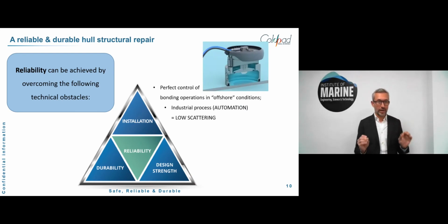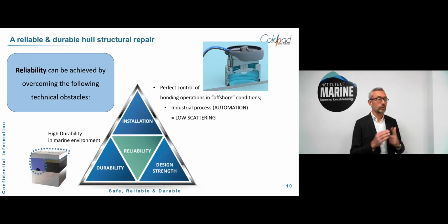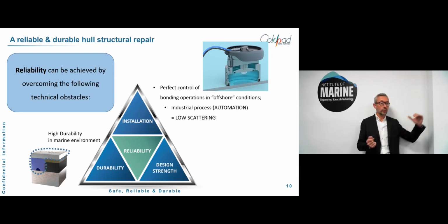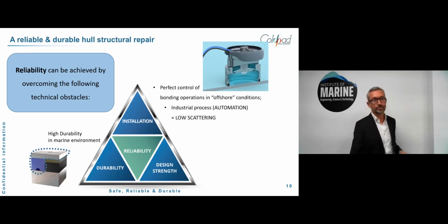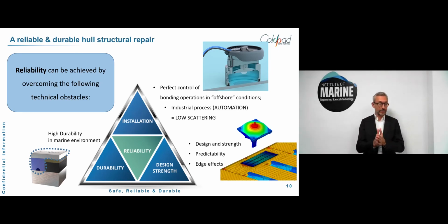And this is where it gets tricky. So what you need is to master the installation condition and especially the humidity level. This is key number one. Key number two is durability. You have to make sure that the water will not reach the bond line. Otherwise, you will have a degradation of your performance, which sometimes will occur, which sometimes will not occur, meaning that it will increase the scattering of the performance during the years. And increasing the scattering is actually the opposite of repeatability, it is increasing the standard deviation, which will affect your design strength. Right? And last but not least is the design strength.